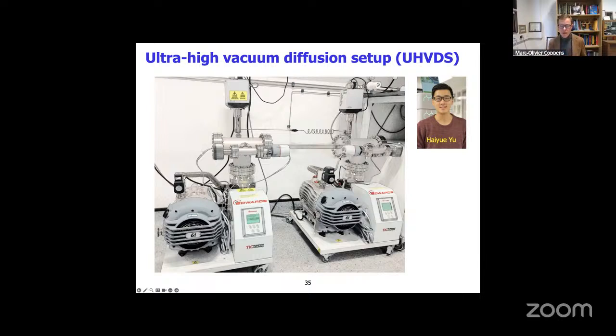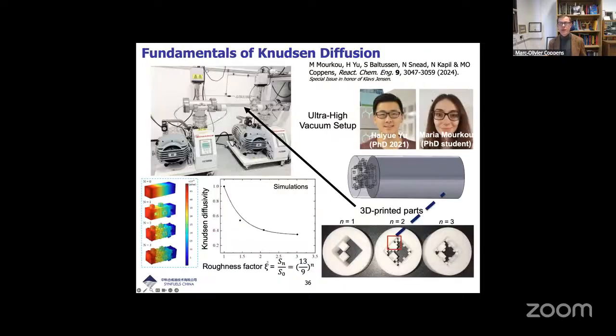And so this was built by a former PhD student, and then recently my student Maria investigated how you can construct different 3D pore models using 3D printing. And so you see that this is the same model that Kourosh Malek used for our kinetic Monte Carlo simulations of diffusion, which allows us to compare directly the Monte Carlo simulations with experimentation. So it's like a blown-out mesopore. It's blown to macroscopic scale, and it's a geometrical representation of what is happening at this nanoscale. And so we recently published this in a special issue honoring another one of the pioneers in diffusion and reaction, porous catalyst, Klaus Jensen from MIT.